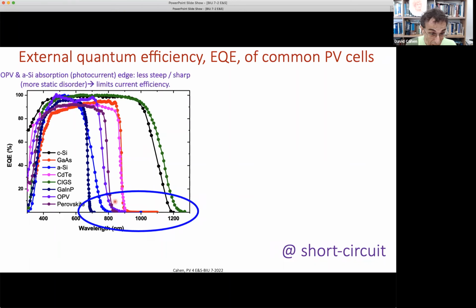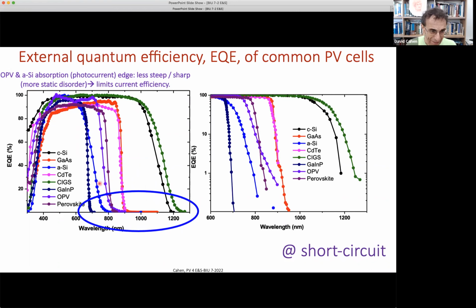Now, there are cells that are significantly worse than others. And they are, in particular, the organic photovoltaics, although it has improved, and amorphous silicon, which used to be commercial, but now is phased out. If we take a close-up of these cells, we see that here is gallium indium phosphide. So yes, it absorbs only a few photons, but it shoots up very sharp. And compare that to something like this organic photovoltaic cell.